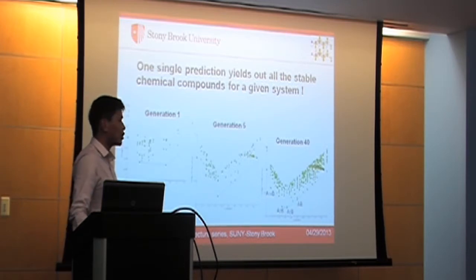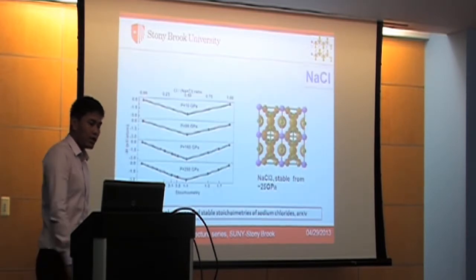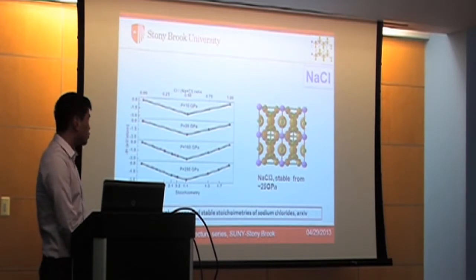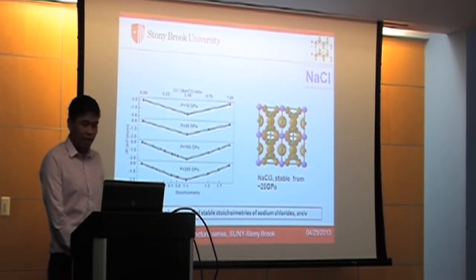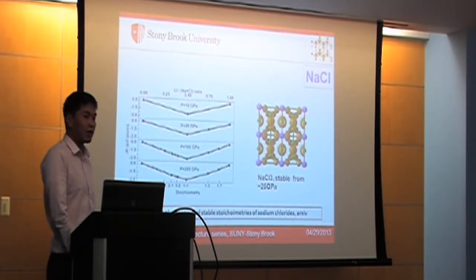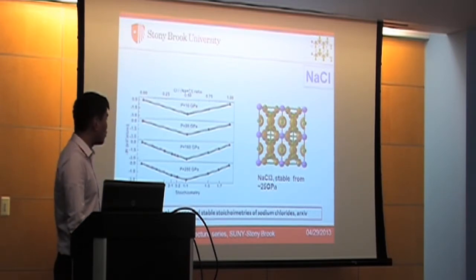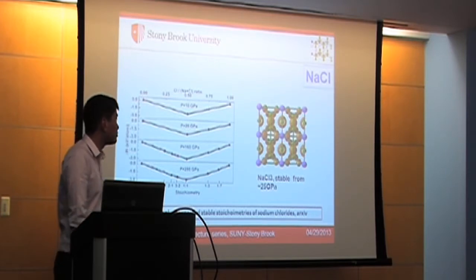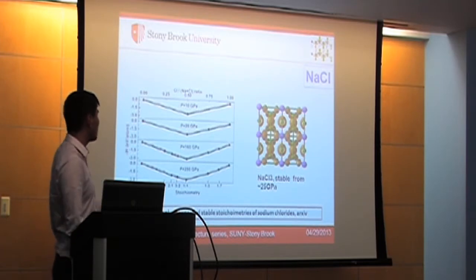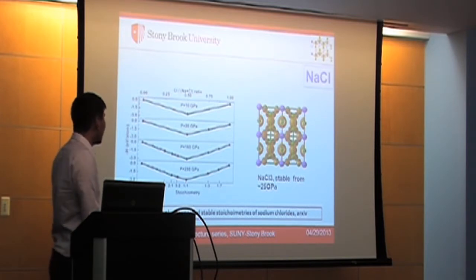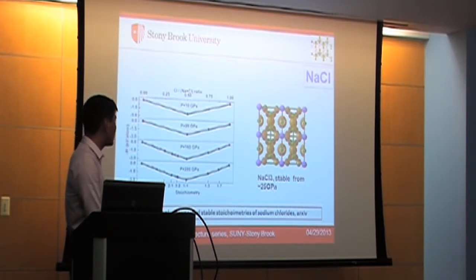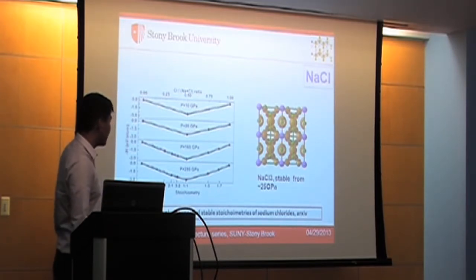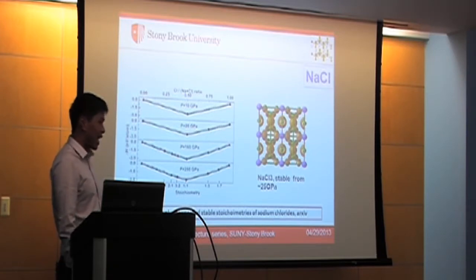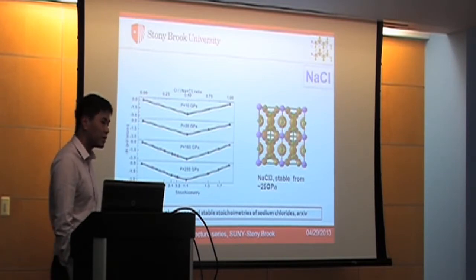All the stable chemical compositions and the corresponding crystal structures. So this is a very useful function. So when we try to apply this to a wide range of systems, the first one is sodium chloride. Sodium chloride is, as we know from the high school chemistry book, a well-known crystal structure and well-known material, and no one can expect anything except sodium chloride structure for this system. But if we increase pressure, we found that this system actually displays a very exotic chemistry. For instance, when we tried like 25 GPa, we found another brand new compound. NaCl3 becomes stable. So in this way, it means that at that condition, these compounds can have equal chance to exist, just as sodium chloride, the one we see every day.